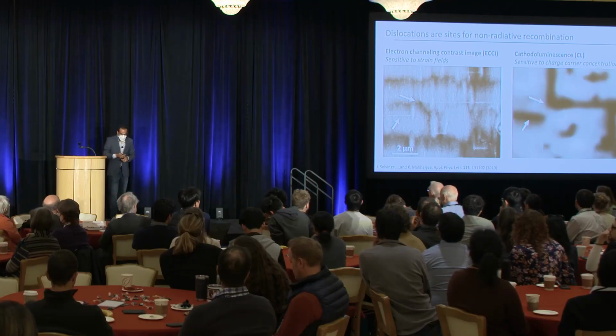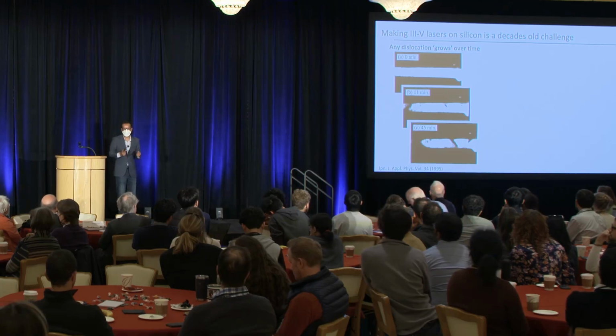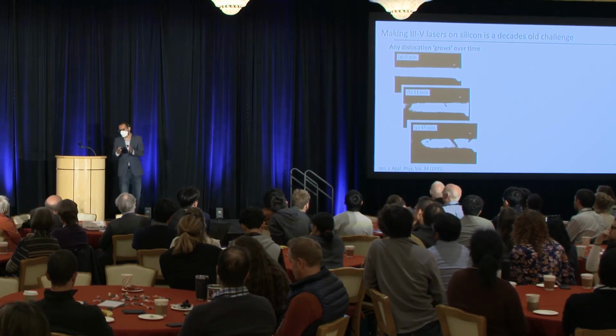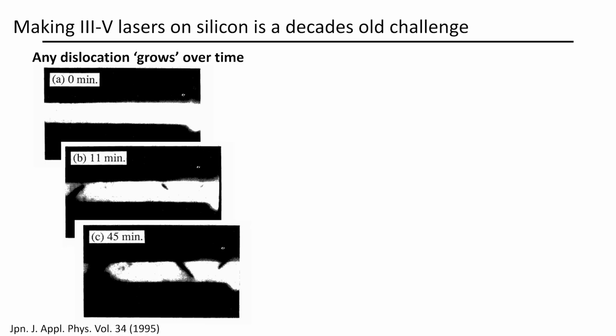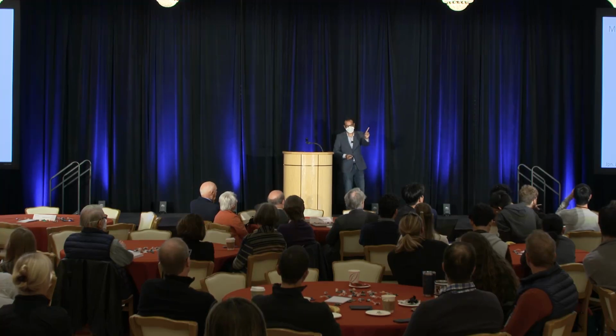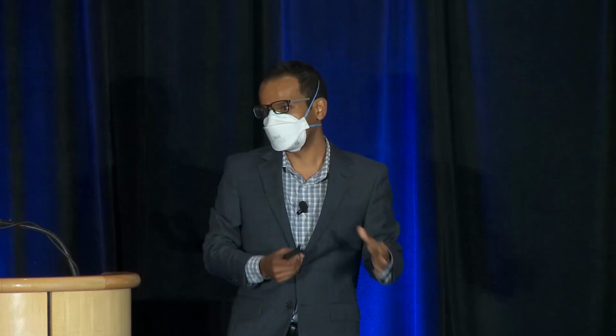Right? If this was the only problem, then this is like having a car with a reduced mileage. It'll still get you from one place to another place. There's a second problem, and that's a bigger problem, which is your car not only has a reduced mileage, it actually breaks down as you're driving. In semiconductors, the dislocations actually grow over time as you're running the device at room temperature. Now, this is data from the Japanese NTT company. Right? In 1995, they were growing these devices on silicon. At time t equals 0 minutes, everything looks nice, wonderful. Right? 10 minutes, 40 minutes, darkness starts to grow in these semiconductors. And these dislocations basically eat up the entire laser over time. So it's not only reduced mileage of your car, but your car breaks down in an hour. And that's why these devices never made it.